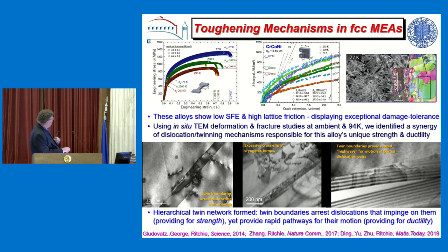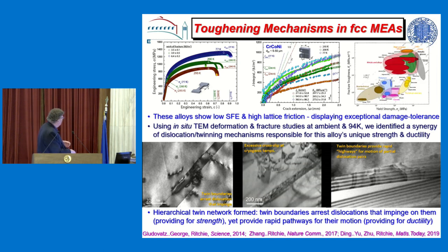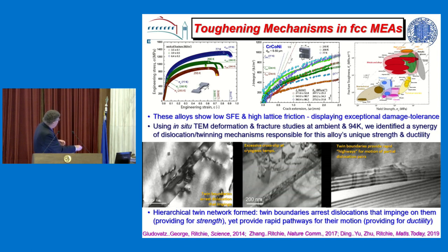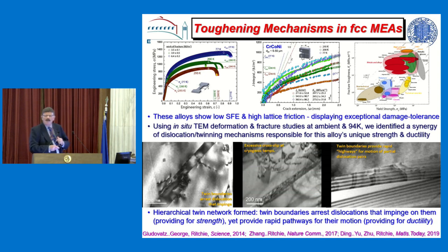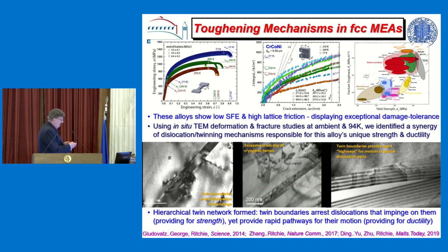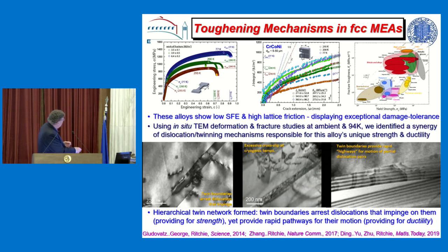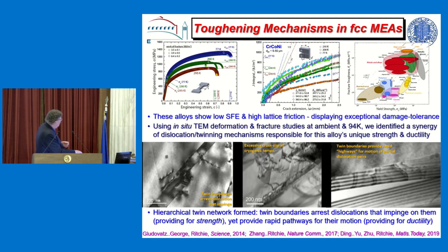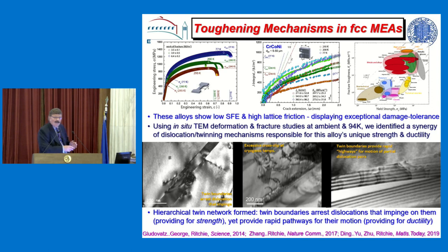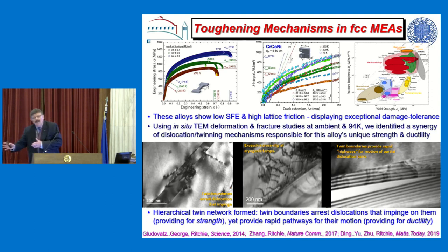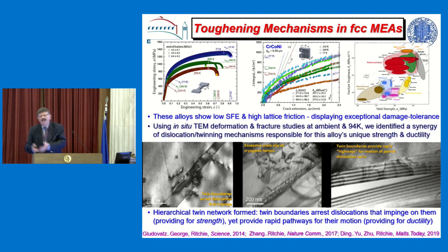So they're fascinating materials, and I won't go through all the details, but it's caused by this region here, which is called strain hardening. Strain hardening hardens the material. The things that move deformation are dislocations, and there's a whole bunch of different mechanisms here. Some of these dislocations coming in are arrested at the boundaries that are formed. They're called twin boundaries. But the twin boundaries, that increases the strength. But if we look at this picture in the third picture here, you can see these are the twin boundaries, but the twin boundaries also are highways for these dislocations to move. So we generate strength and we generate ductility.